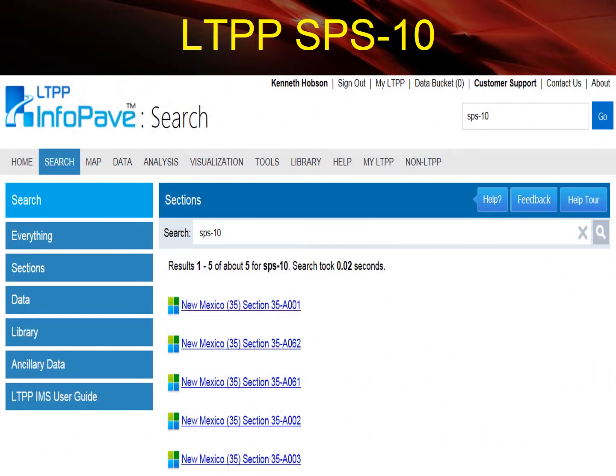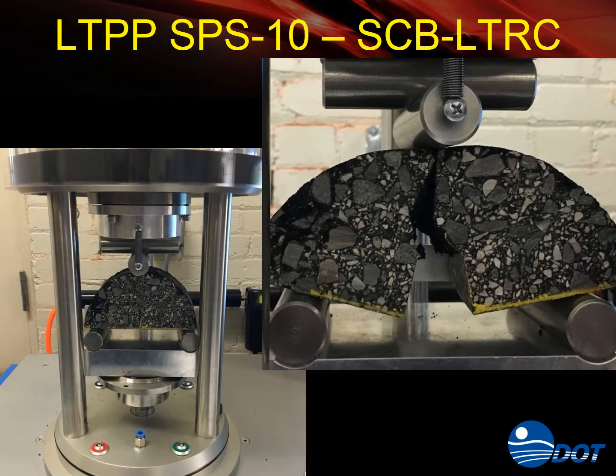But if you go to infopave.com, you can look up LTPP projects and put in SPS-10. You'll see data for New Mexico. You don't see Oklahoma's data because that's only updated once a year, so our data is not in there yet. If you're not familiar with a semicircular bend test, here it is performed in the AMPT, all the way to failure. And they had these different notch lengths that we cut in here. There's 3 different lengths. And of course, the bigger the notch, the faster it cracks, right? Stands to reason. And you plot these on a plot, and then you see how they perform.